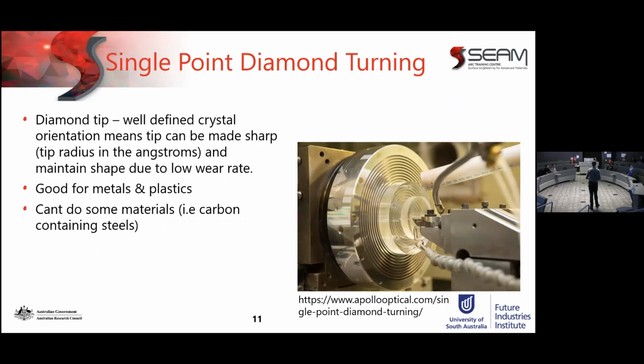Okay, single point diamond turning. So now we're getting into very fine machining that can bring about a very low surface roughness and near optical finish. A diamond tip is selected, machined with the right crystal orientation to make it hard wearing, and it will hold its shape during machining, and then you can get very fine surface finish with it. Good for metals and plastics. There are some limitations. Anything containing carbon will end up reacting with your diamond tip and basically you chew through diamond tips like that.